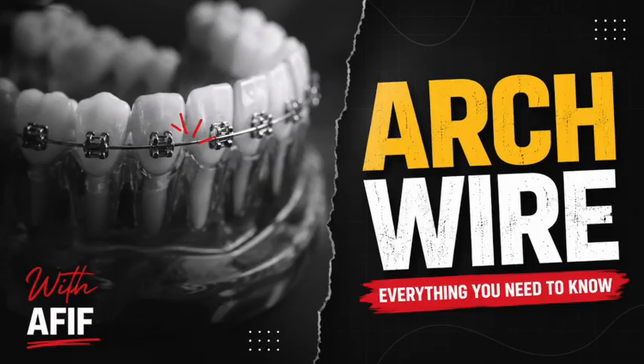Because it's trying to be flexible. Exactly. As the wire bows, it loses its straight trajectory, the wire hits the sharp internal corner of the bracket, and it binds. It gets stuck. The tooth literally digs a notch and gets stuck in the microscopic bend it just created in the wire. So the very thing that makes Nitinol amazing, the fact that it effortlessly bends to absorb stress, creates a literal speed bump for the tooth when you try to slide it. Exactly. It's too flexible to act as a monorail.